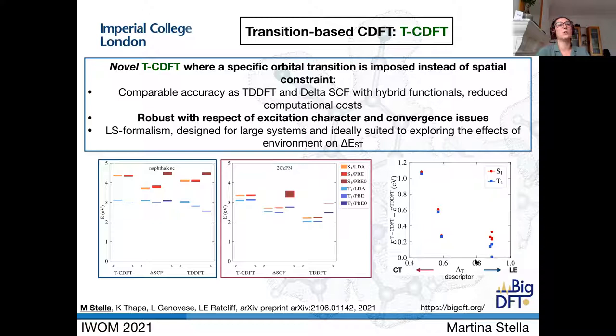We developed this method within the wavelet-based code BigDFT, which offers linear scaling. We applied T-CDFT on a set of molecules with both local and mixed excitation. We find comparable accuracy of our method to TDDFT and delta-SCF with hybrid functional, but with reduced computational cost because we only apply T-CDFT with semi-local functionals.